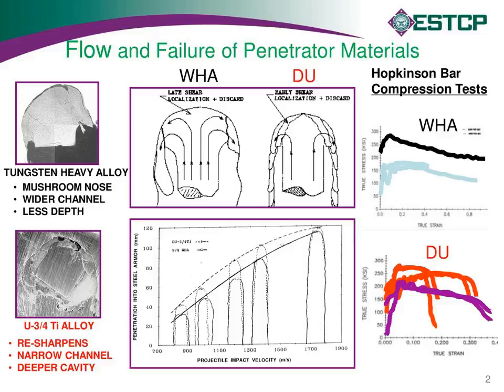But late in the penetration process, in both cases, as the rods are eroding away, they're starting to slow down because the elastic waves can travel back and forth in that rod more and more quickly. So they both start rapidly slowing down, and then you start seeing the same behavior that you saw at the lower velocities the whole way down, that the DU tunnel is noticeably narrower. So it isn't a change in behavior, it's just that the relative importance of this adiabatic shear behavior versus this plastic mushrooming behavior changes with velocity.